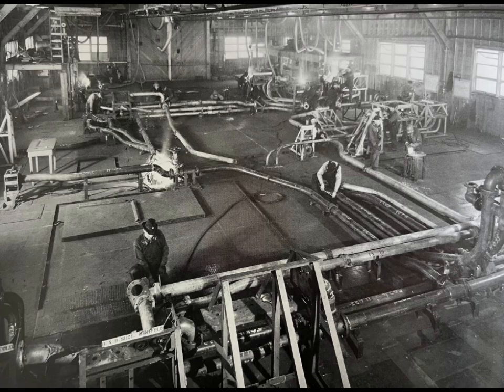The steel used in early war production became brittle at temperatures common in North Atlantic winter. Welded construction allowed cracks to propagate across continuous plates faster than in riveted construction, where rivet holes interrupted crack paths. Poor welding technique created stress risers where cracks initiated. The combination was occasionally catastrophic, but the response wasn't to abandon welding.